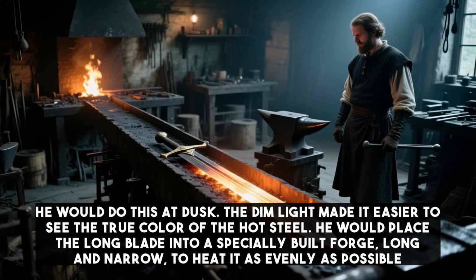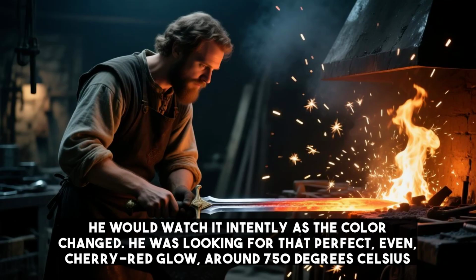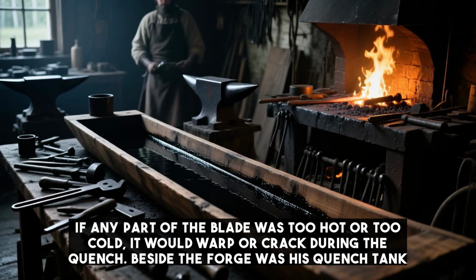He would place the long blade into a specially built forge, long and narrow, to heat it as evenly as possible. He would watch it intently as the color changed. He was looking for that perfect, even, cherry red glow around 750 degrees Celsius. If any part of the blade was too hot or too cold, it would warp or crack during the quench.